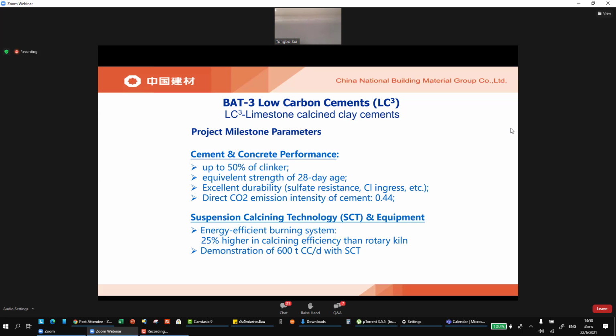We expect the clinker factor of the low carbon cement to be 50%. But even with 45% of clinker replacement, we expect to achieve equivalent 28-day strength compared with pure Portland cement without any addition of blending materials. And the new low carbon cement can also exhibit excellent durability and so forth. The second important milestone for this project is to develop the suspension calcination technology.